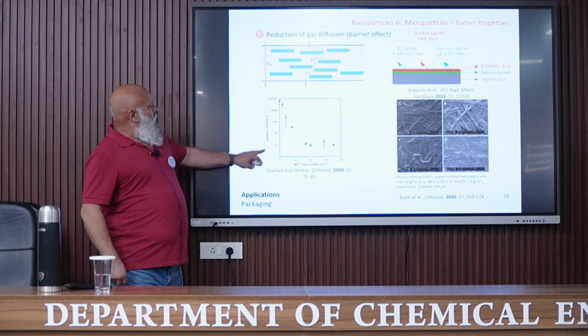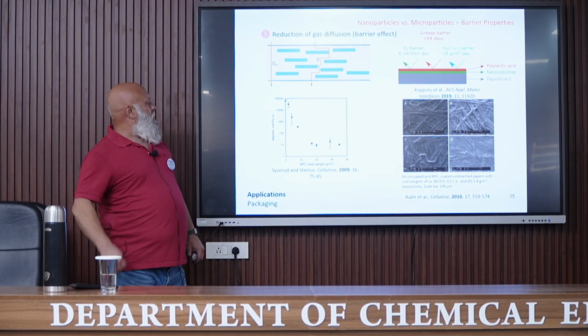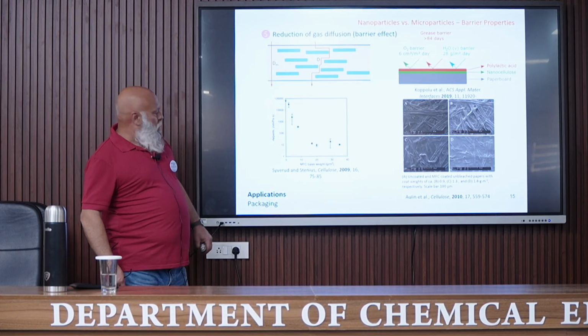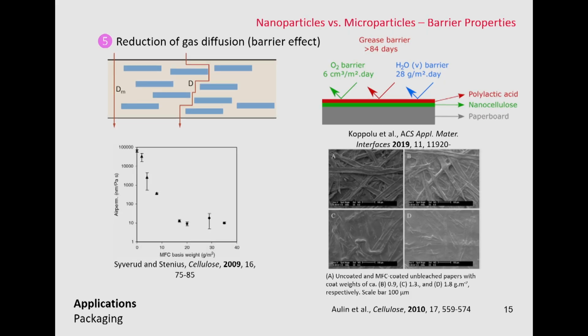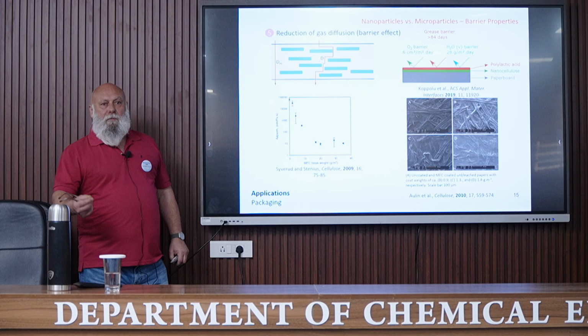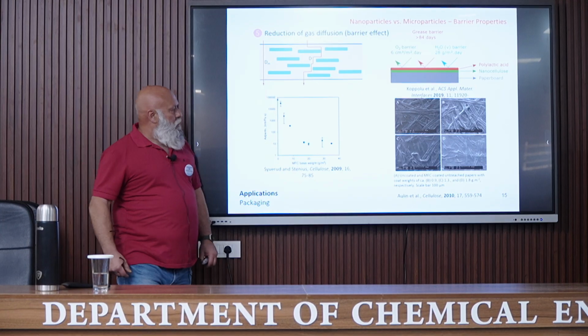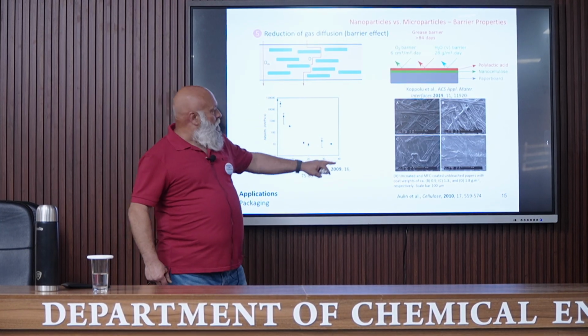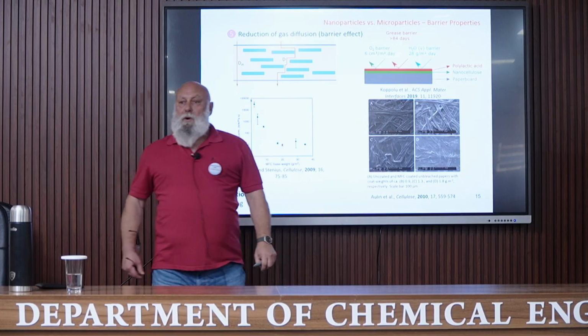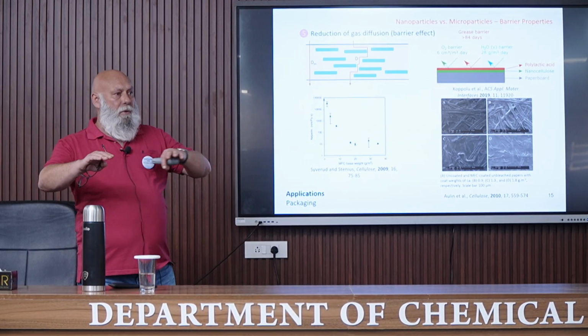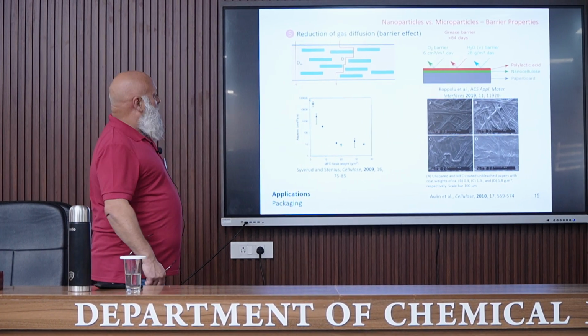This is a different example in which the substrate was paper or cardboard. I don't remember exactly. Yeah, it was paper, sorry. And this paper was coated with different amounts of cellulose nanofibrils. And the air permeability was measured as a function of the amount of nanofibrils on the surface. We can see this decrease because, of course, when coating the paper with the nanofibrils, it's possible to fill the voids between the fibers.